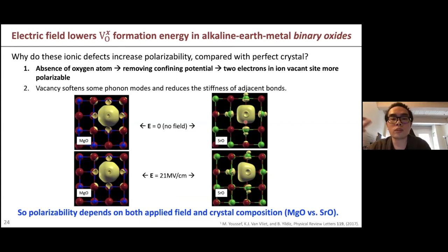Oxygen was acting like a confining potential, and once it is removed, the two electrons basically become more free in the vacant site, and then it can be polarized more. So that's why for the defect itself, we can have a higher dipole moment under the same field strength, and that's how the field can assist the defect formation when we apply it.